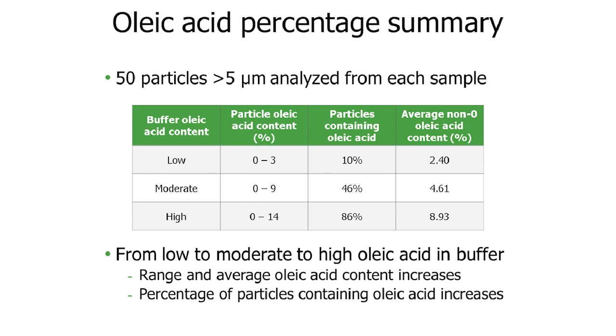When the buffer had moderate oleic acid content, the oleic acid content in the particles increased. So in that case, just under half, 46% of the particles contained oleic acid. And those particles contained up to 9% oleic acid per particle. Following this trend, when the buffer had high oleic acid content, so did the particles, up to 14% oleic acid per particle. Further, a significant majority of these particles did contain oleic acid. 86% of the particles in this sample were found to contain any oleic acid at all.